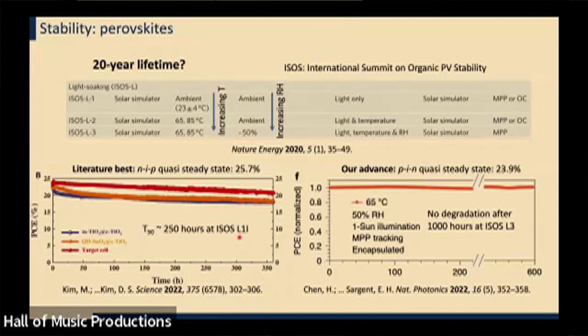It's also led to a lot of scientific investigation of where these limitations in performance are coming from. So here I'll just highlight some of our work from earlier this year. We made a device that actually flipped upside down the perovskite solar cell architecture. That allowed us to deposit it onto a completely inorganic hole transport material, a nickel oxide hole transport material. And that allowed us to pass one of these reliability tests. There's a bunch of standards that have been established in the solar sector. To pass the one that's an accelerated lifetime test, one that occurs at 65 degrees C, and to report the absence of degradation over 1,000 hours.